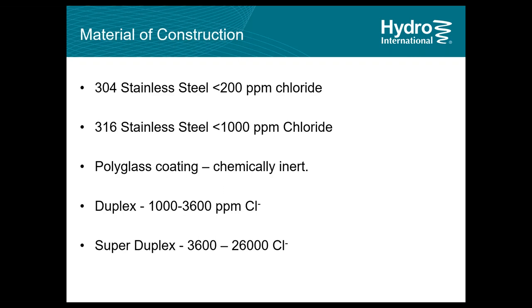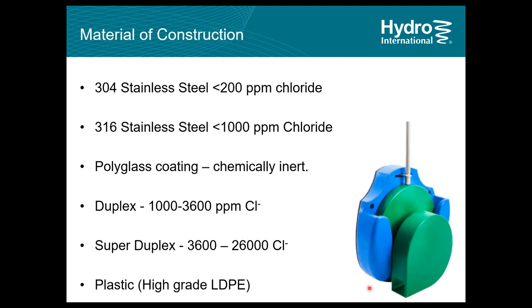If the customer doesn't want a coated unit, we also offer optional duplex or super duplex steel. These grades are suitable for chloride levels up to 3,600 ppm for duplex and 26,000 ppm for super duplex. For small flow and head ranges, we can supply plastic units made of high-grade LDPE, with a discharge range of 1 to 20 liters per second and up to 2 meters of hydraulic head.